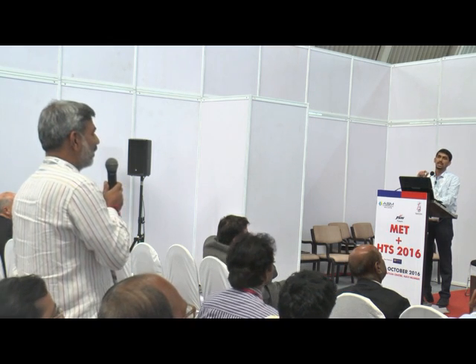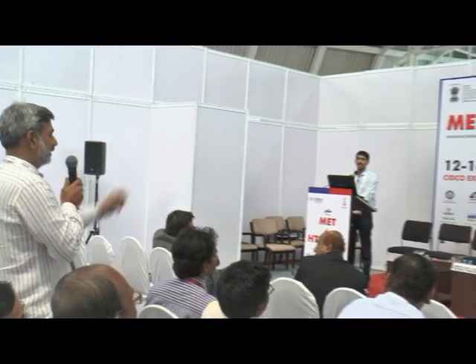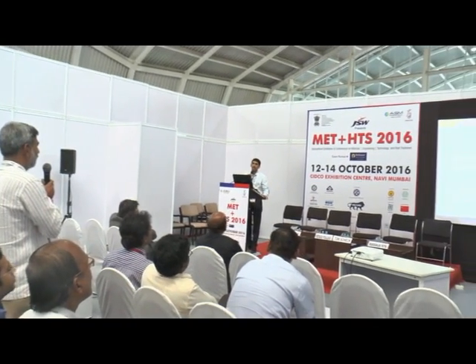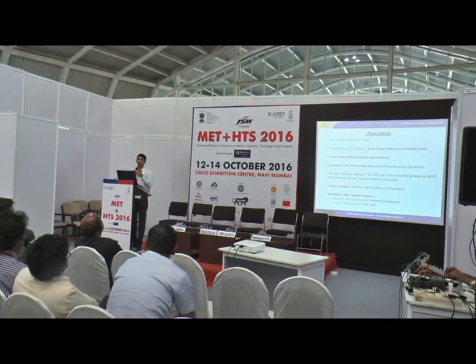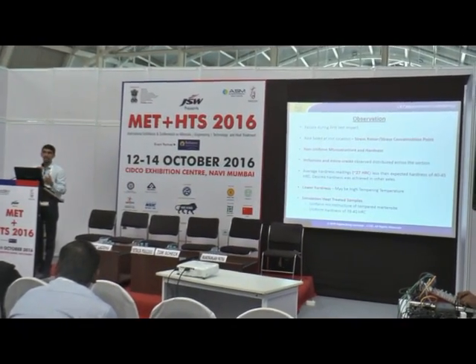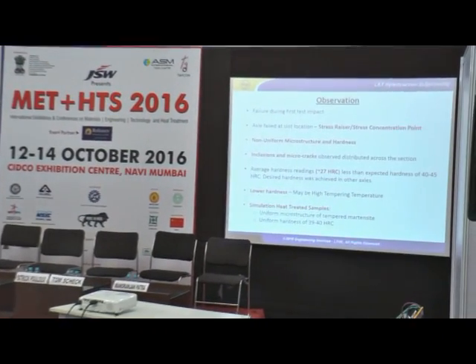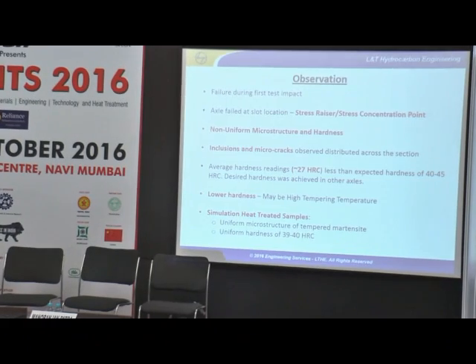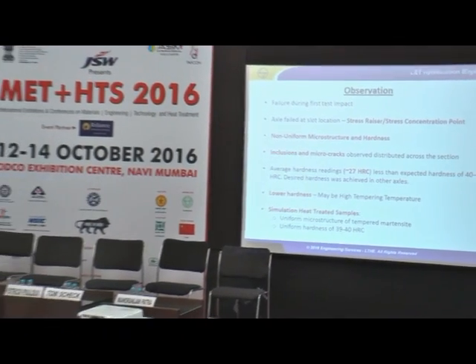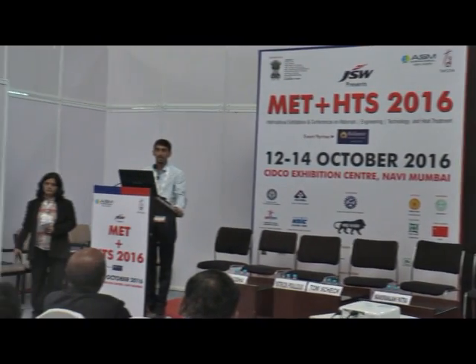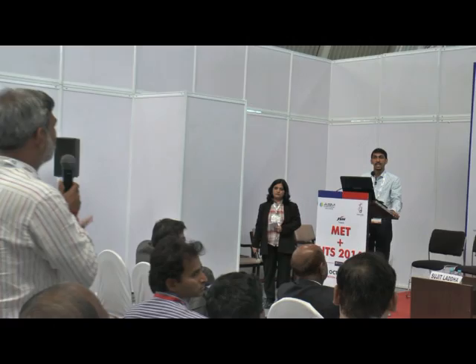In the microstructure, if you recollect from the slide, I've shown multiple. Just before this. Yeah, you mean to say this one. See, the microstructure we obtained across the cross section was non-uniform. This is one of the hypotheses we are proposing could be the reason for the lower hardness. It might be the case that the tempering temperature was high, but throughout the cross section area we could not get the tempered martensite. So the tempering temperature may be higher, but the tempering time may not have been given properly. Yeah, exactly. That may be the main reason.